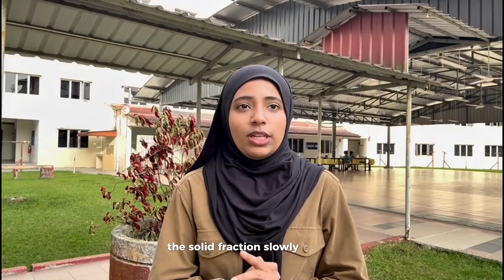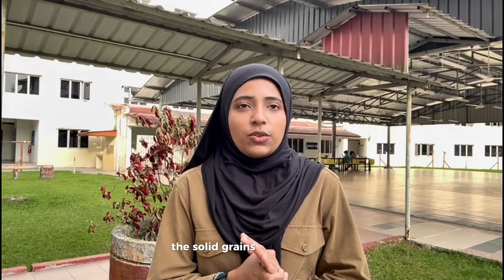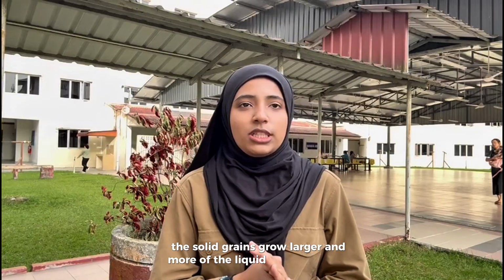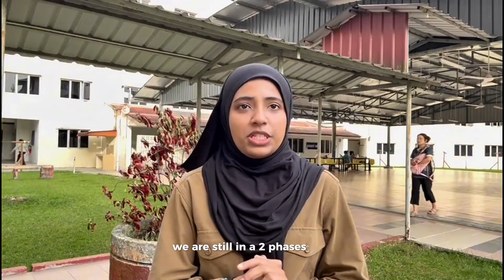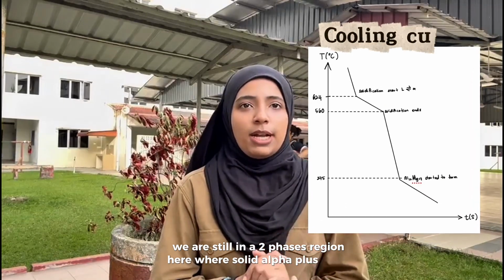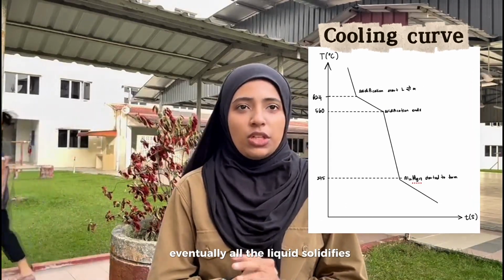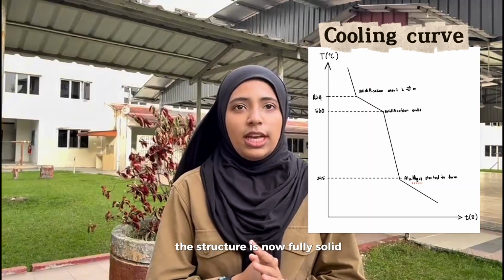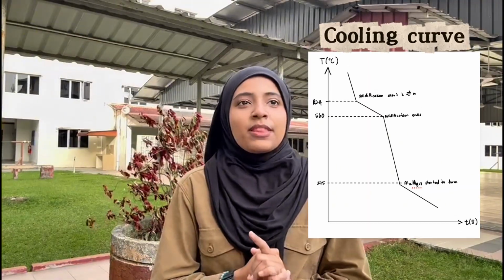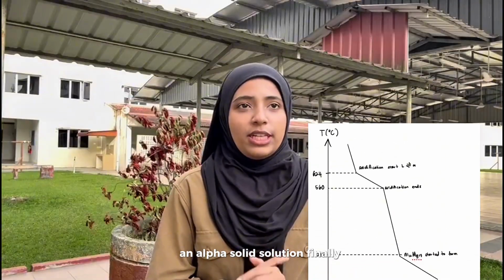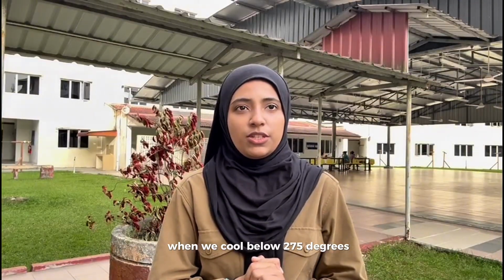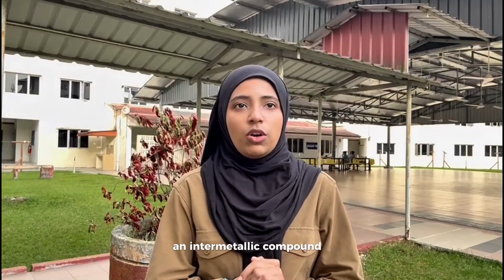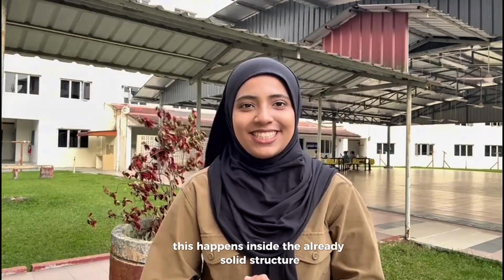The solid fraction slowly increases as the temperature drops. Continuing to cool, the solid grains grow larger and more of the liquid turns into solid. We are still in a two phase region here, solid alpha plus liquid. Eventually, all the liquid solidifies. The structure is now fully solid and consists of only one phase, an alpha solid solution. Finally, when we cool below 275 degrees Celsius, an intermetallic compound called Al12Mg17 precipitates out within the solid grains. This happens inside the already solid structure.